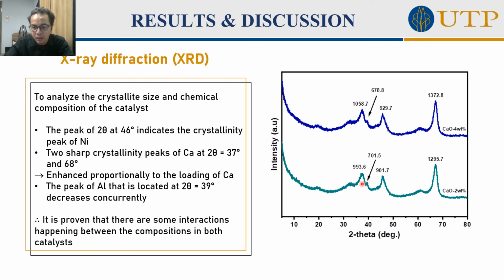As you can see here, the peak of Ca for 2% is 993.6, and for 4% is 1058.7. The same goes for the other crystallinity peak of Ca here. The nickel peak is also enhanced with higher loading of Ca, which is for 2% 901.7, and 4% is 929.7. And the peak of Al that is located at 2 theta 39 degrees, which is the small one here, decreases concurrently. So for 2% it is higher, which is 701.5, and for 4% is 678.8. From here we can conclude, and it is also proven, that there is some interaction happening between the compositions in both catalysts.